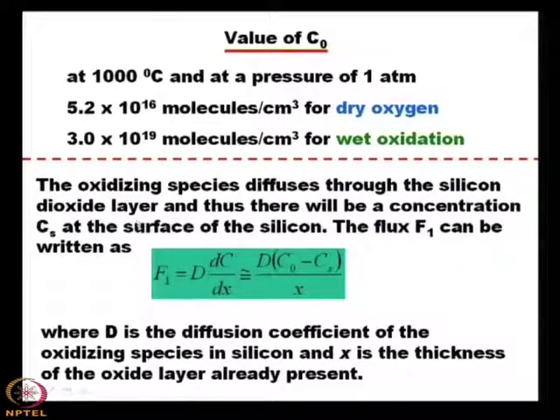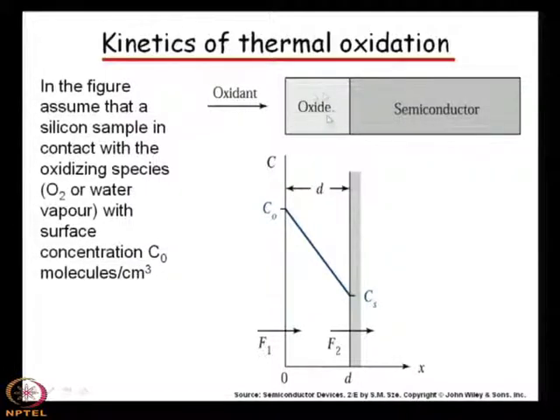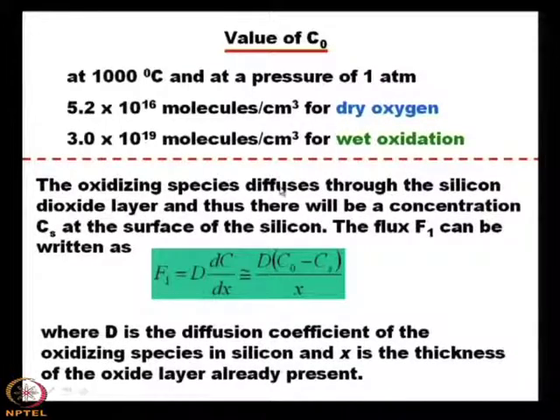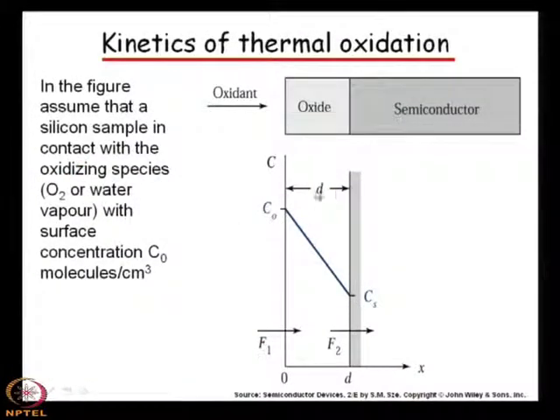Then the oxidizing species diffuses through the silicon dioxide layer, because remember, there is already an oxide layer formed on the semiconductor surface. So, now the oxidant must diffuse through the oxide layer to reach the semiconductor surface, and once it reaches the semiconductor surface, it will react with the semiconductor to form SiO2. So, the oxidizing species diffuses through the silicon dioxide layer, and thus there will be a concentration Cs at the surface of the silicon. Here, d is the thickness of the oxide already formed, and the oxidizing species must diffuse through the oxide.